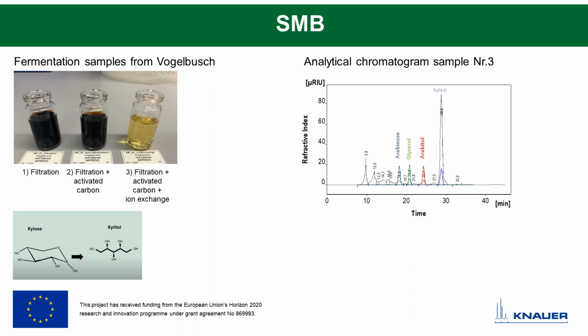Visual comparison clearly showed the decolorization of the third sample compared to the other 2 samples. As the accumulation and thus blockage of chromatographic columns by impurities should be avoided, only the sample treated by activated carbon and ion exchange was used for further experiments. Analysis of this sample revealed a high content of xylitol and low amounts of arabitol and glycerol.